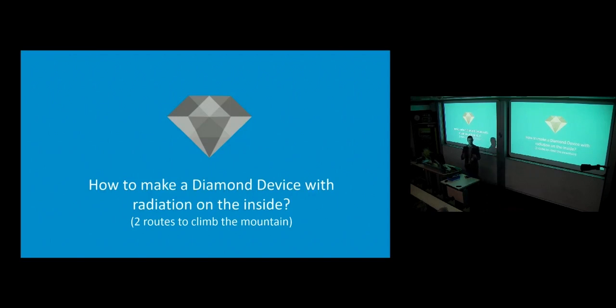And actually, the beta particle conversion efficiency in theory is about 95% efficient. So it's incredibly efficient. Now, there are other types of betavoltaic available, but they all work on the principle that you have an emitting material and a collecting material, and there is always a gap or a discontinuity where they come together because there's a material mismatch. You get absolutely huge energy losses across the gap, so the efficiencies are incredibly low. And what we've done in betavoltaic technology is throw away the gap, throw away the discontinuity. It's just a single structure, and therefore we can't get those losses because it's not possible. There's no interface.